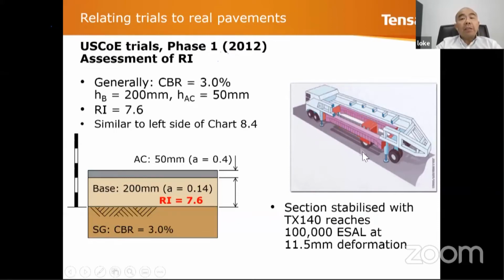Okay, so for this test, we have carried out way above 100,000 ESALs. An ESAL is about 80 kilonewtons of loading. So you can imagine what a huge performance test this has been. And you can see that even with 100,000 ESALs and with geogrids, the deformation is less than 12 millimeters, which